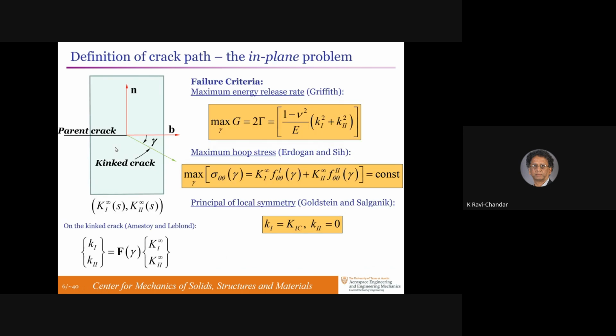So the mode 2 crack in the NB plane looks like this. Here's the parent crack surface, and it's loaded under some loading of K1 and K2 in the far field. The question is, what is the angle at which the crack would grow, and what dictates the load level at which it would grow? This is obtained by using the maximum energy release rate criterion. The crack finds that angle gamma along which the energy released is the largest, and therefore it's easiest to crack along there. I'm assuming it's an isotropic material. Fracture toughness doesn't change with orientation.